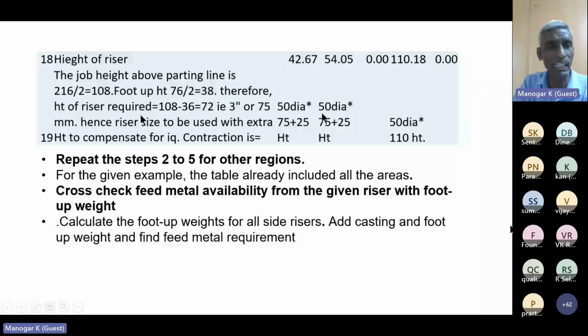The job height above the parting line is 108 mm, and with the foot, it is coming to 72 mm. So you can go for 3 inch, but above the flange you have to keep some allowance for safety, for the liquid contraction. So we are keeping 50 by 100 mm. So this is the riser height we arrived at now. So repeat the steps for all the other areas like this.